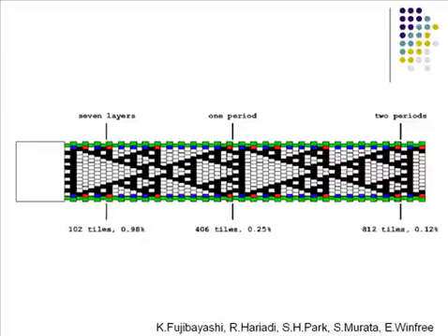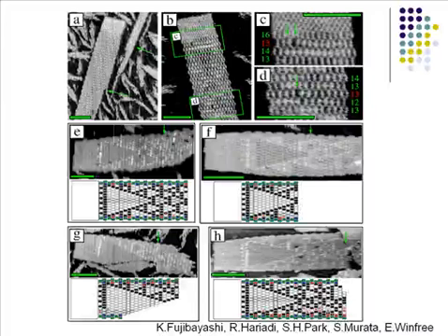And so we can compare this template with the experimental results to evaluate the error rate. And this is the experiment result. And so you see a good correspondence between the experimental result and the simulation template. And by comparing those images, we can actually count the error rate.